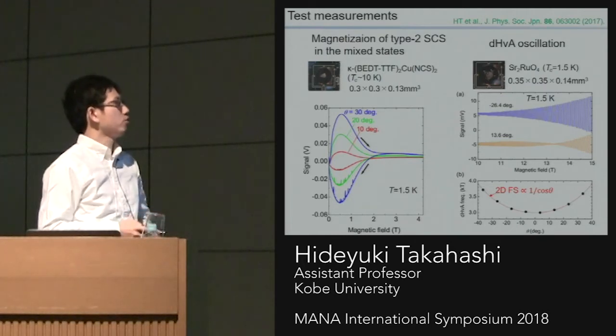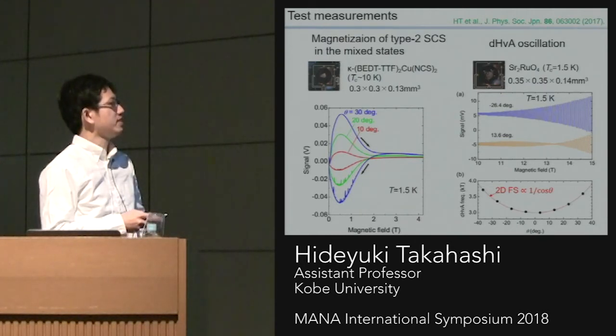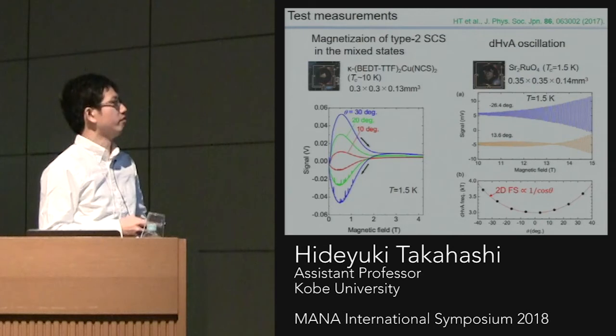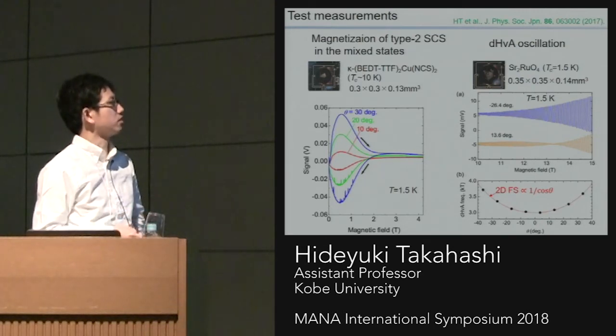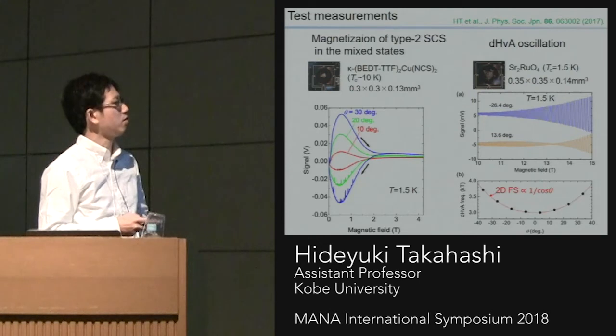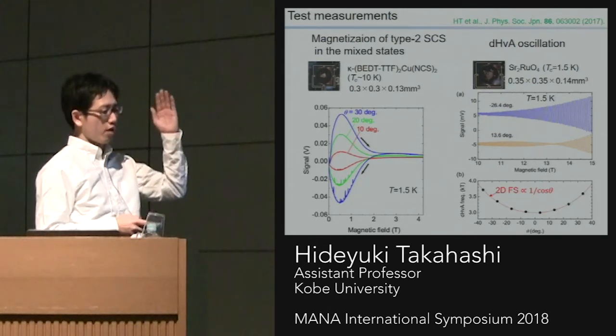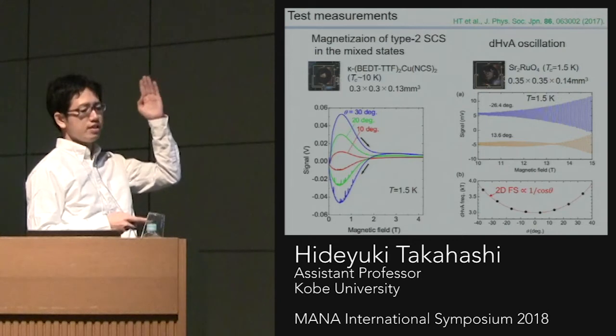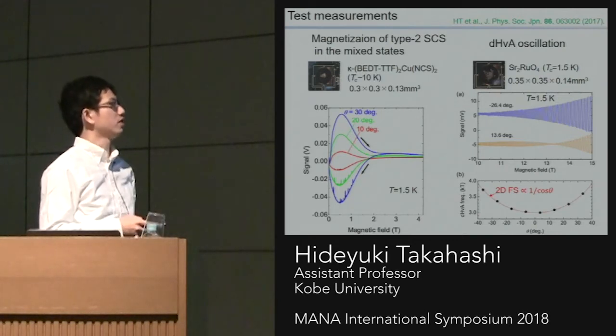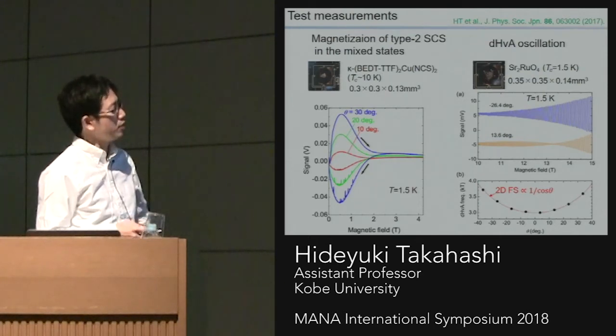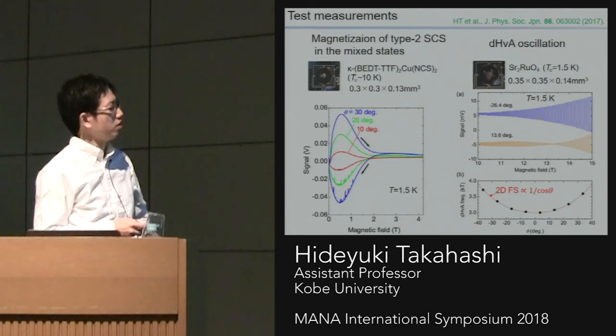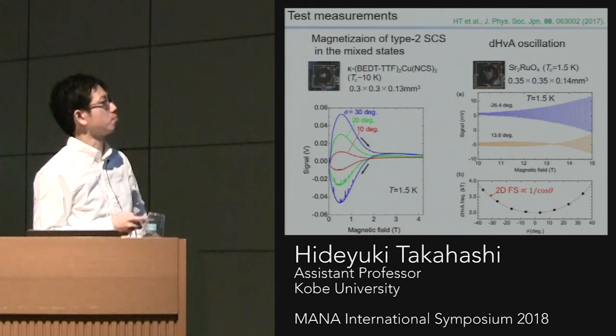And this is the data. We can observe the hysteresis curve. This is a typical behavior due to the vortex pinning in type 2 superconductors. And here we define this angle as the angle between the sample's C-axis and the magnetic field direction. As the angle rotates, this hysteresis becomes large, and at the same time, the magnetic field at which these 2 lines merge shifts to the higher field. These are characteristic behaviors for the layered